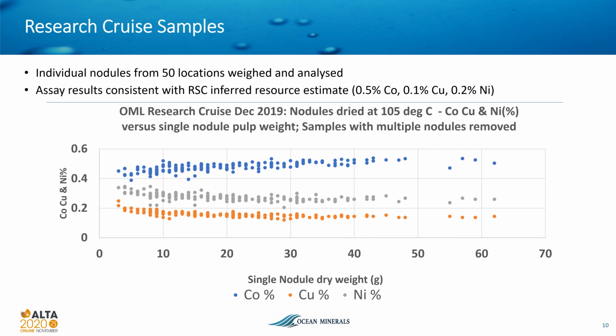This slide shows the assays for cobalt, nickel and copper of individual nodules collected across the 50 drop sites. An average of 4 individual nodules of different sizes were assayed for each drop site. Even though the drop sites covered a distance of over 20 nautical miles, there was remarkable consistency in the results. As can be seen from the graph, cobalt assays increased slightly with increasing nodule dry weight. On the other hand, both nickel and copper assays decreased slightly with increasing nodule dry weight.